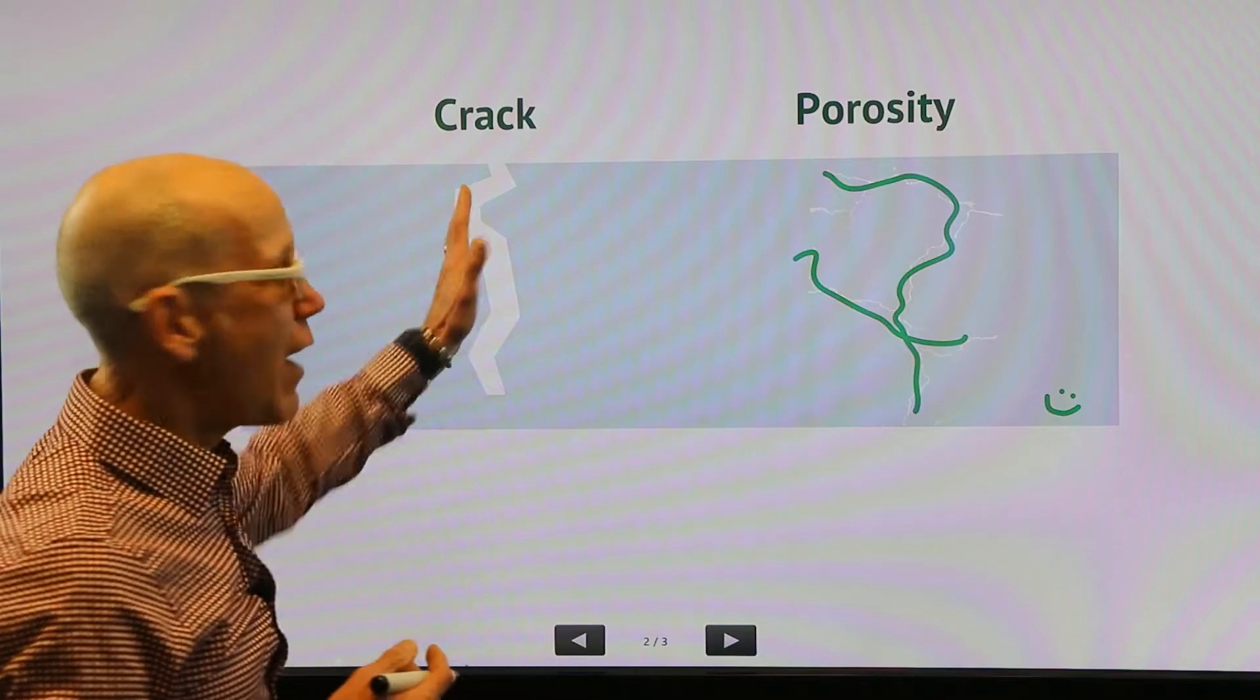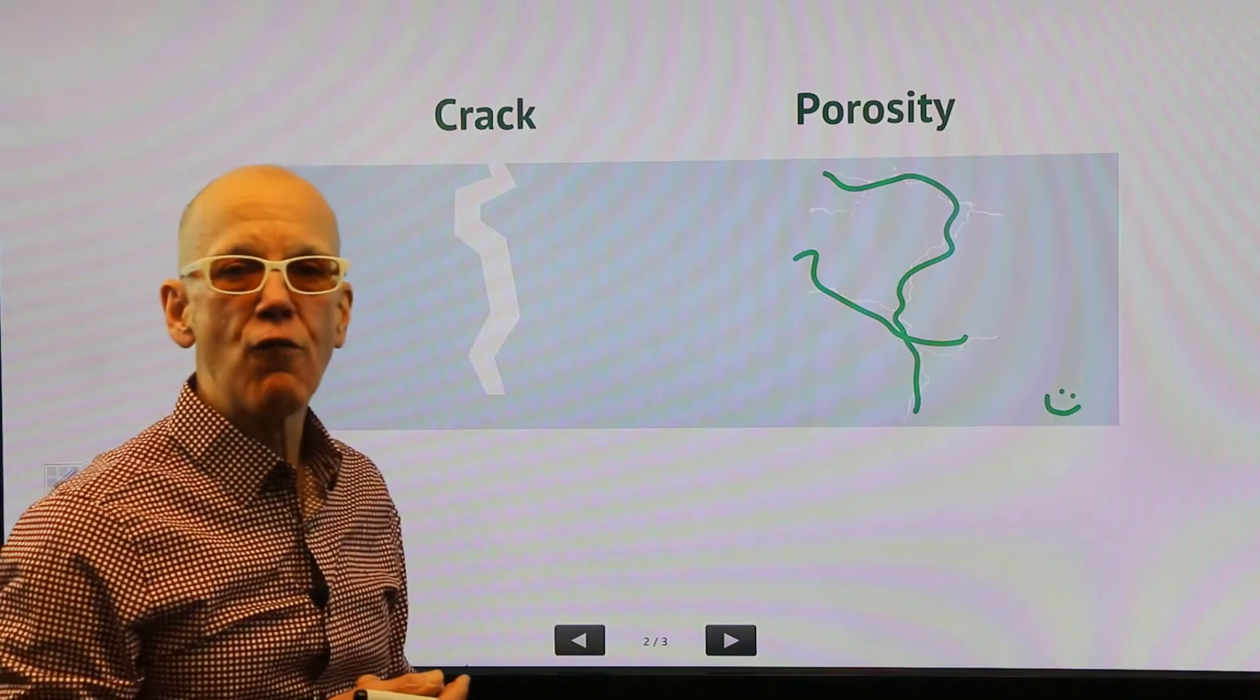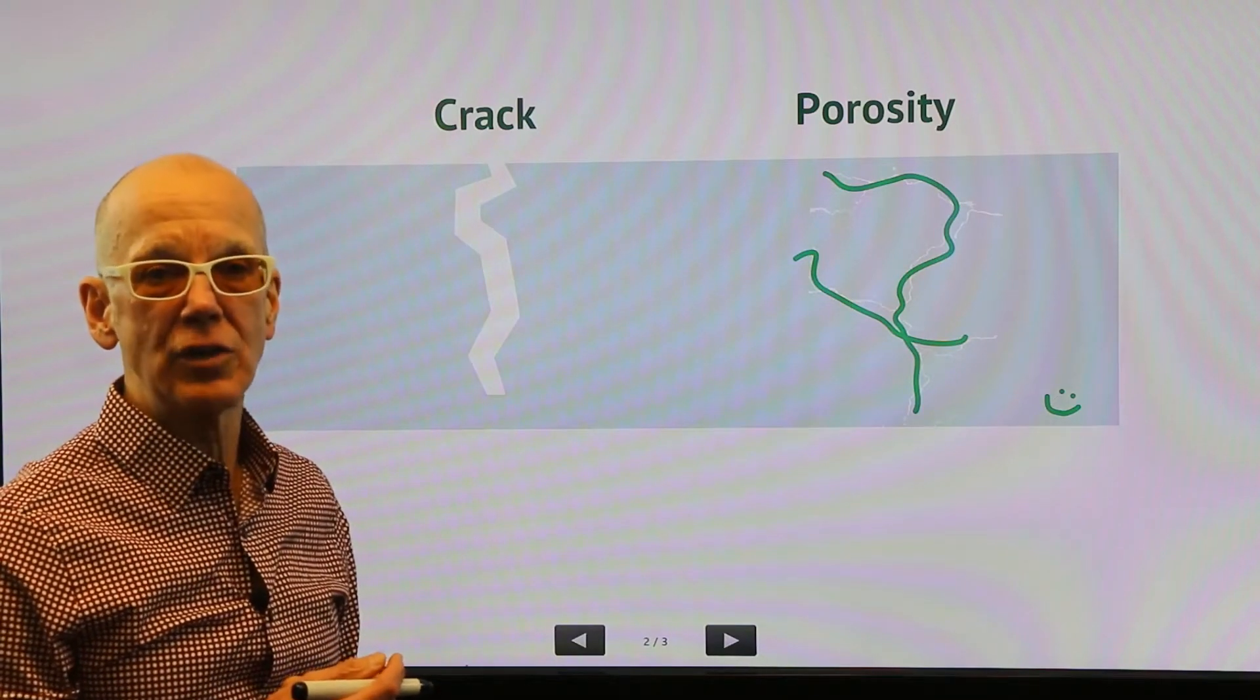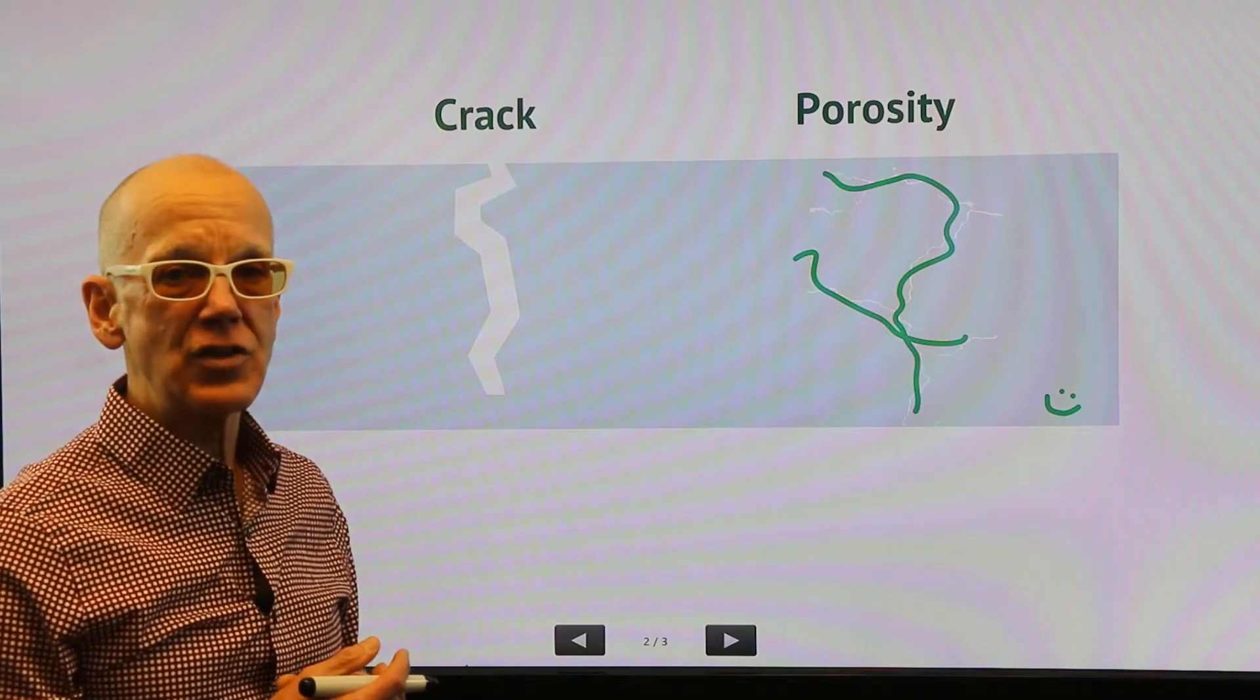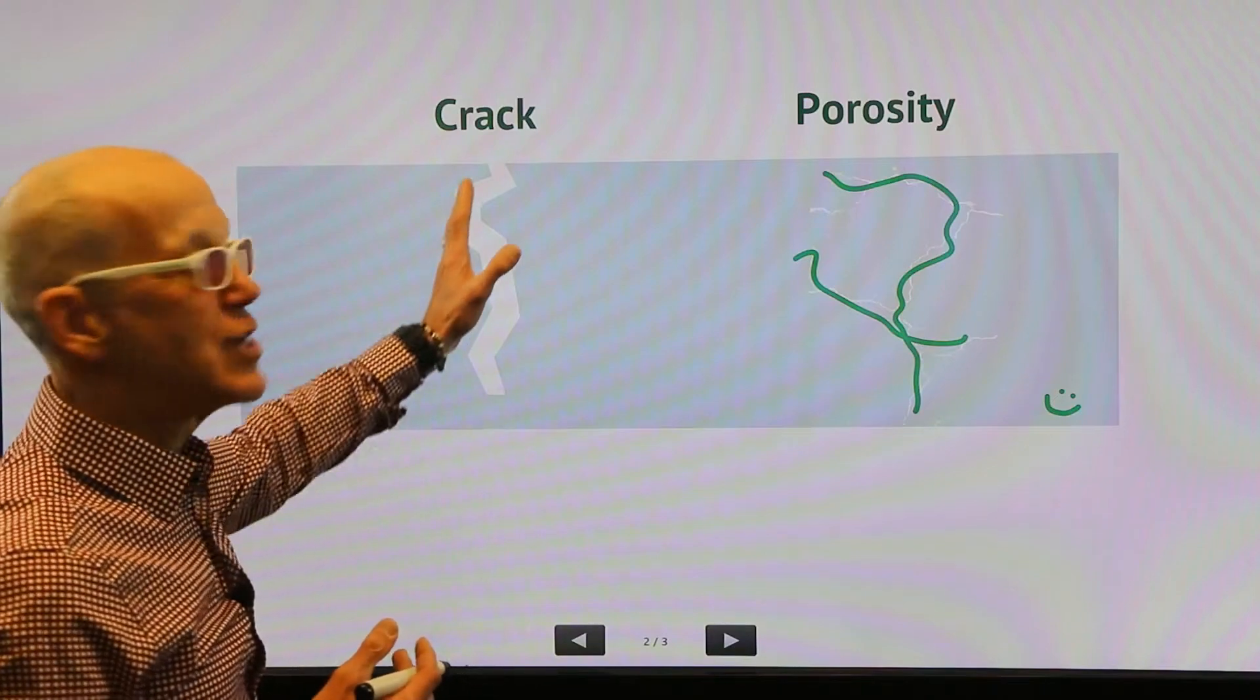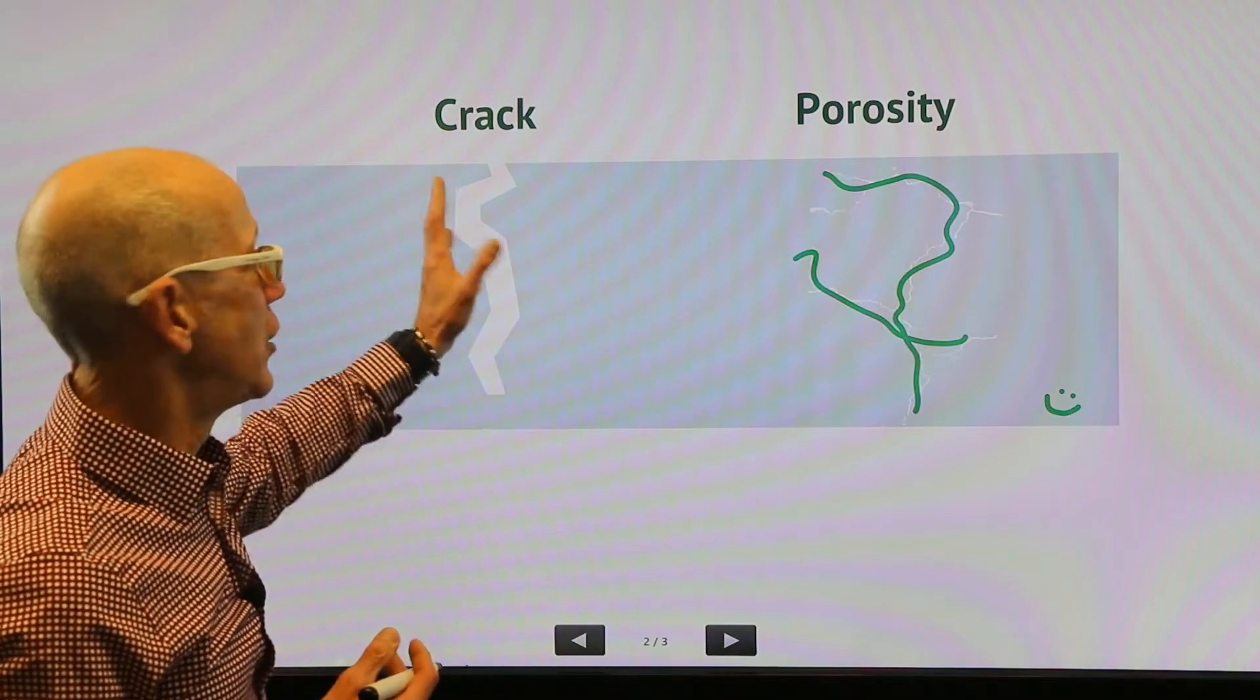Now if you take a look at a crack, on the other hand, a crack forms post-solidification, typically in ejection, sometimes in handling after the casting is ejected. But the crack is not static and can move.